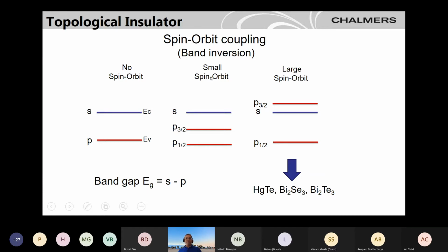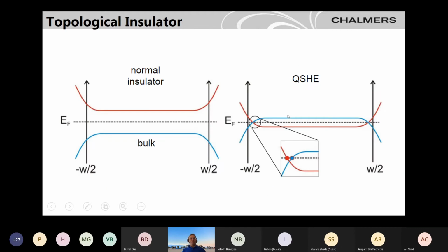But when you have a small spin orbit coupling, what happens? This P level is close to the nucleus, they split. But when you increase the spin orbit coupling with heavy elements like mercury telluride, bismuth selenide, bismuth telluride, there are now thousands of compounds you can find. What happens? This P level can go above the S level because of the spin orbit splitting, and then this system is called an inverted band. So instead of S minus P, you define P minus S. So it's an inverted band structure, and that is the origin of the topological insulators.